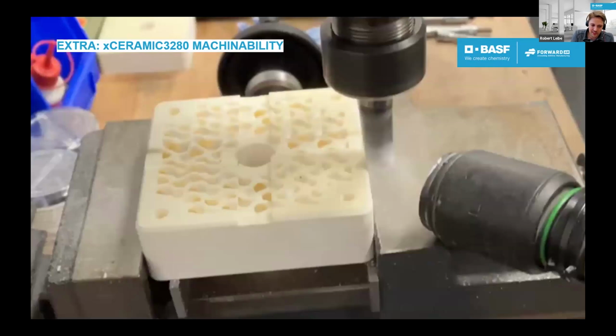So as I said, the material is rather on the brittle side. So you really want to make sure your printed mold insert is not warped, does not stick out of the base mold, or is in any way dimensionally too inaccurate. So a quick machining of the backside can already erase most of the problems we see. Because when the two mold halves are not aligned properly and the injection molding machine closes, these printed inserts will crack. So milling the backside flat will reduce this problem already by a lot.